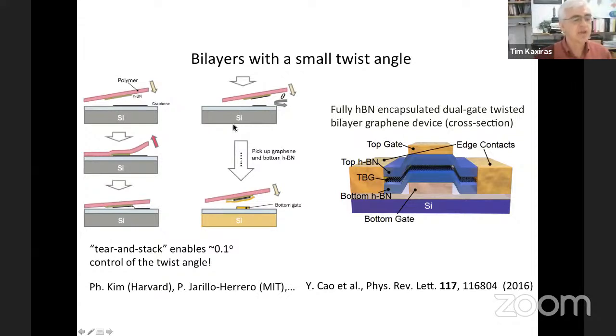And then they put the one half on top of the second half to create the precisely controlled twist between the two layers. So these are experiments that were pioneered by Philip Kim at Harvard, Pablo Jarillo-Herrero at MIT, and many other groups. And then the whole thing is sandwiched between the top and bottom hexagonal boron nitride layers to create a device. So that's a very brief overview of the experimental technique, and it really is wonderful and has made this whole field possible.